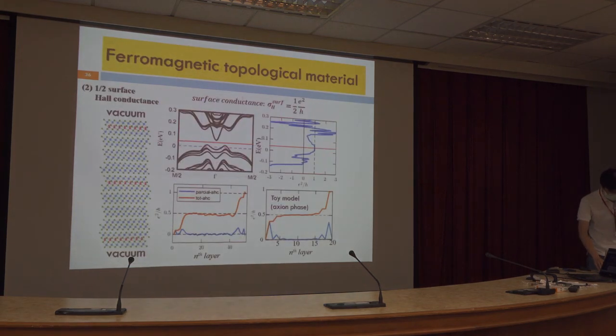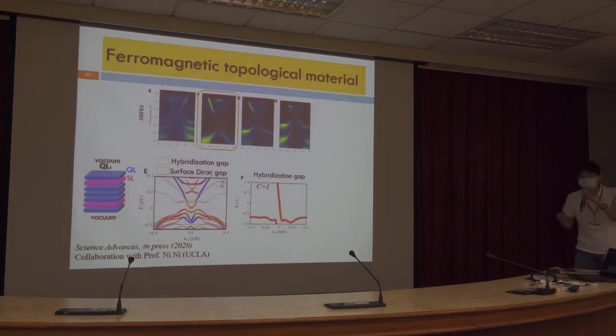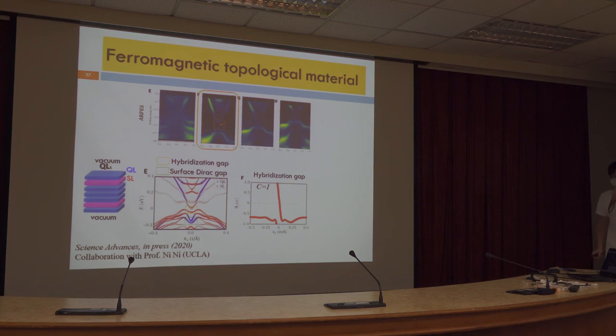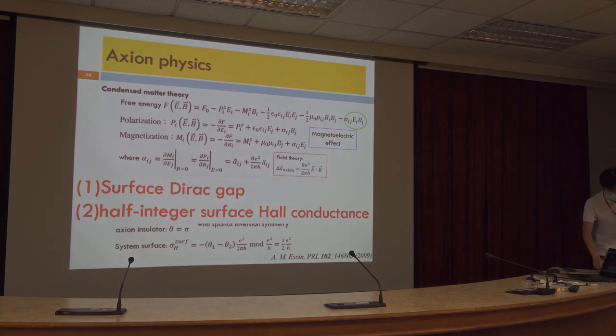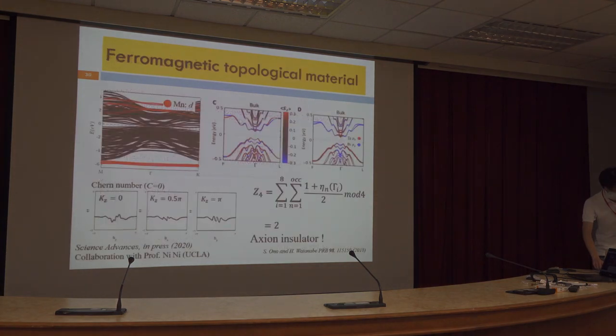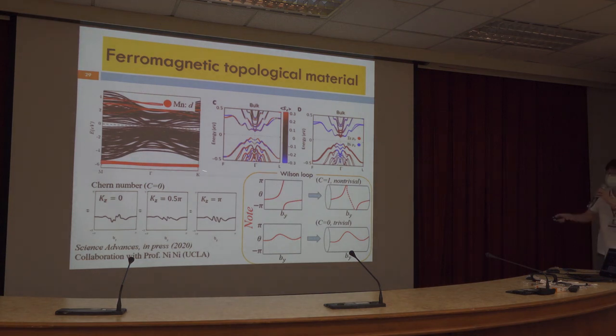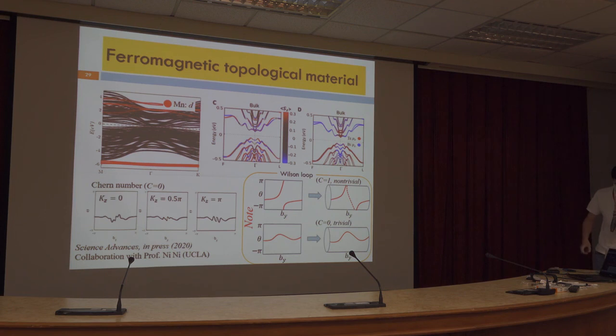Very good question. We do not fully solve this problem. The only answer is to compare with experiment. You can see there is a very large gap in experiment. We still get the gap in DFT, but this gap is smaller than in experiment. We can trust the DFT if the system does not have a strong correlation effect. In our system, we see the d orbital is far away from the Fermi level, so we can ignore the strong correlation effect in the DFT. So our result, I think, can be convincing.